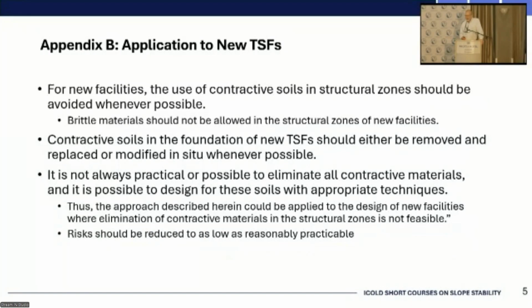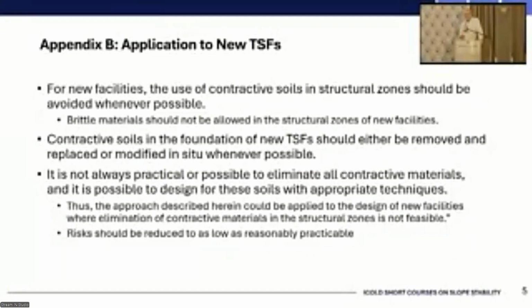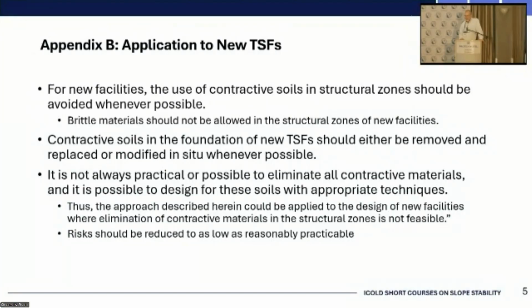It's important to note that whenever possible, we should eliminate contractive materials from our structural zones. And we certainly need to avoid using brittle materials. To knowingly go into a design with a brittle failure mode is really not acceptable anymore, so we should try to avoid them. This applies both to materials in the embankments and materials in the foundation. If you have materials in the foundation that are subject to brittle shearing, brittle failure, then they should either be removed and replaced or modified in situ. But we recognize it's not always possible, or at least practical, to remove all contractive materials, and therefore you can design against it, and that's why we feel the approach can be used for new facilities.